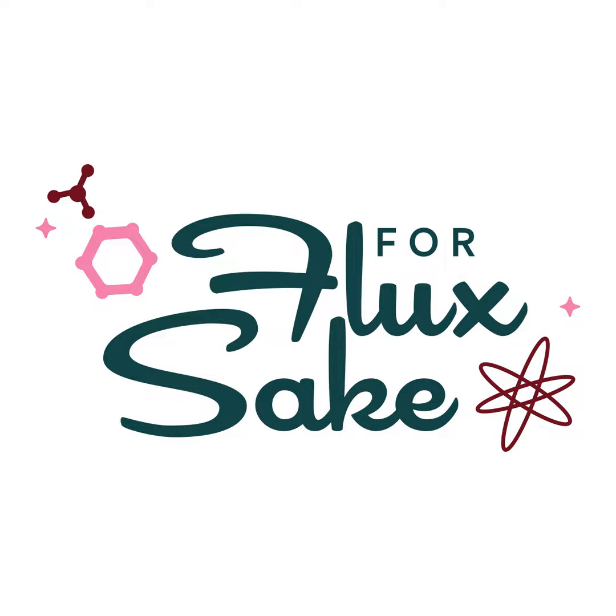And so granular manganese is just a gritty form of manganese dioxide. Ilmenite is a material that's half iron and half titanium. It's about 50-50 of both within one material, but it's iron that causes the problem, and then you're sort of stuck with the iron. And magnetite's just a form of iron. So I think most of the time they're using granular manganese because it removes the issues.